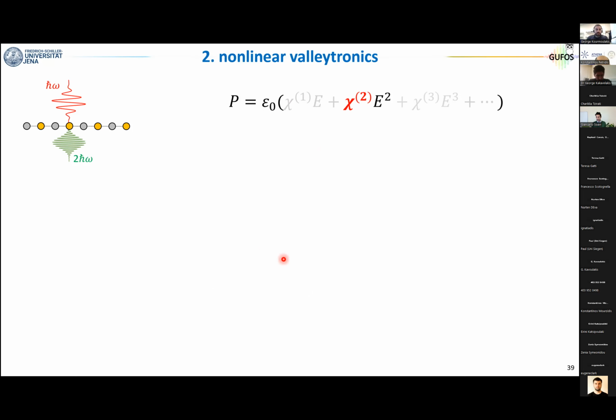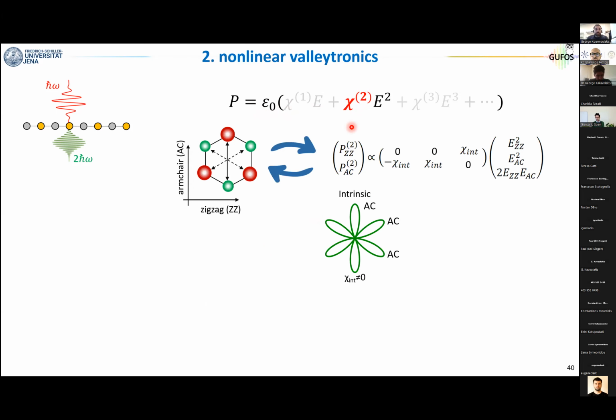The answer is yes. And for that, I go back to the polarization and I focus on this term, the chi2, that I only mentioned before. It's the second order nonlinear response of the material. Now, if I go a bit more into the details, sorry if there is a bit of algebra, but this expression here basically tells you that if we know that we have three armchair directions, and we know what is the polarization of the incoming electric field, so the incoming electric field can be either along zigzag or along armchair or along a superposition of the two, then the second harmonic will be emitted either along zigzag or along armchair.